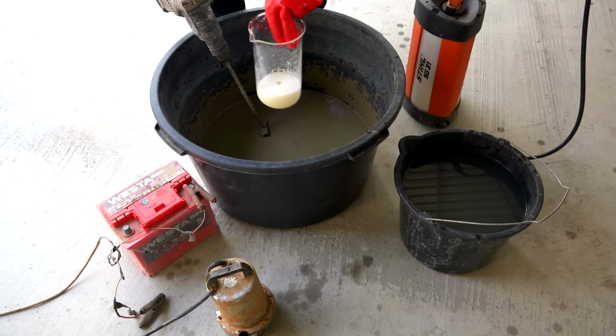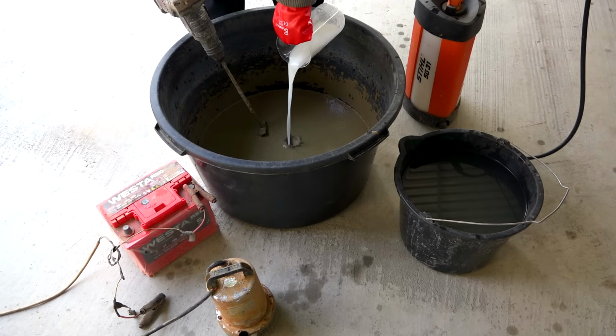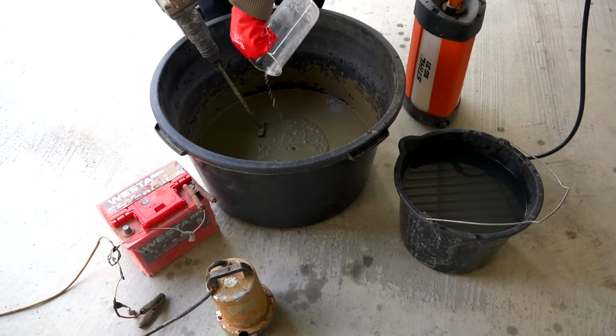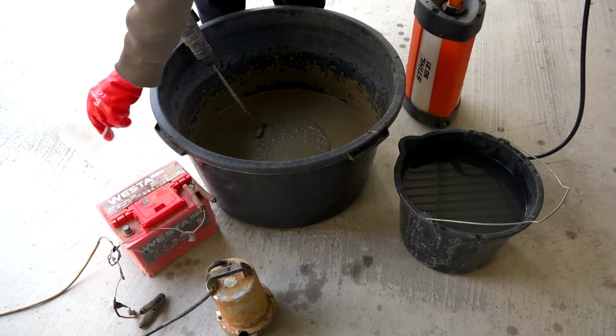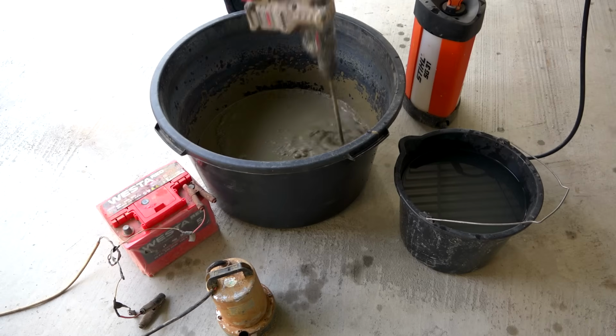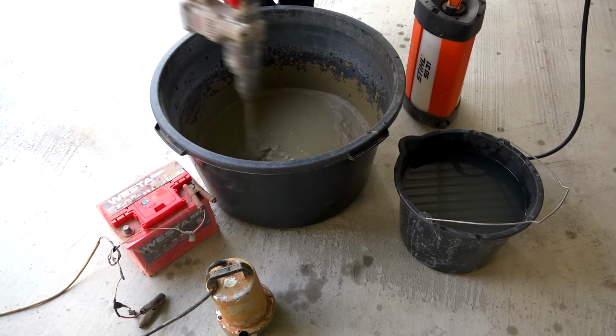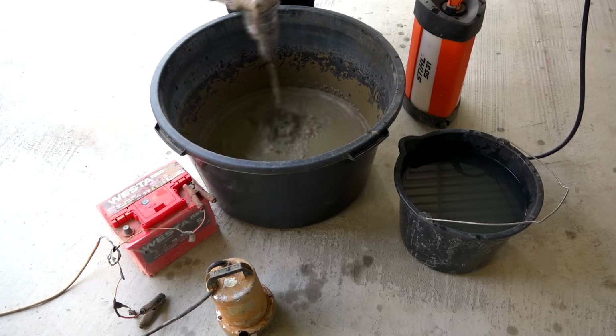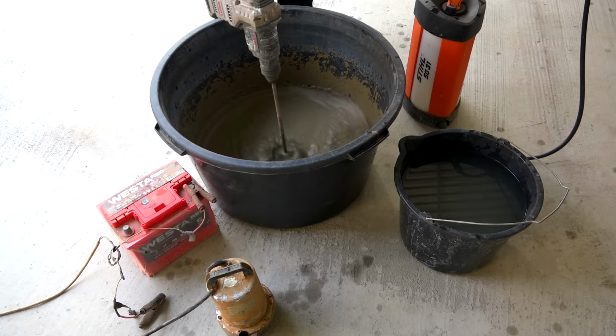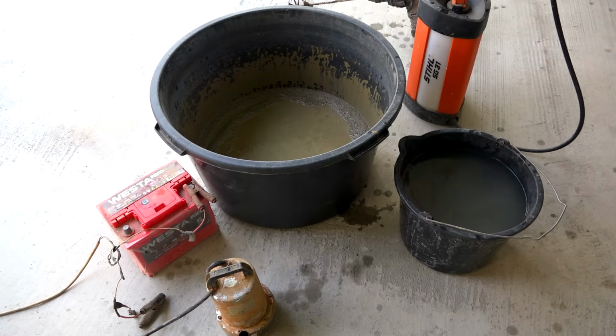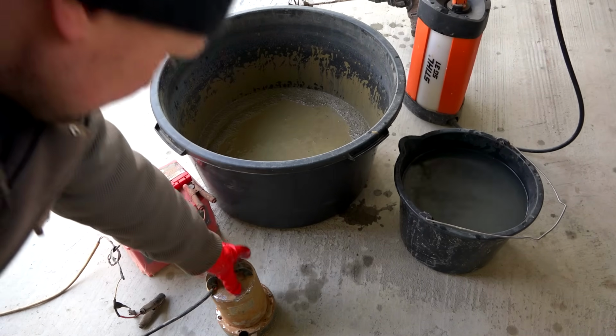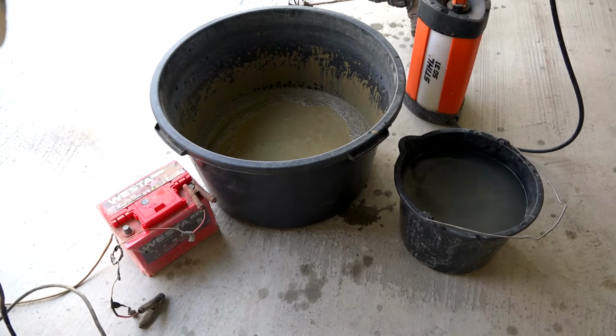After mixing and softening the solution, I add 50 mg of a simple solution to the pulp. This solution will create bubbles and foam, and I'll use diesel fuel as a particle collector. I'll continue mixing with a mixer, and this time, for flotation, I'll need a 12-volt water pump. I'll use this water pump as a pulp mixer.